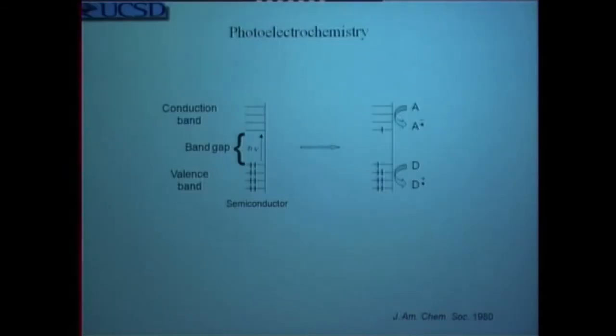Similarly, if there is a hole in what was the highest filled orbital, that hole can be filled by accepting an electron from the donor. So by using absorption on a titanium dioxide particle or an electrode, you can get to the same place that you could by water splitting in that simple experiment you remember from your elementary school days. This is what we refer to as photoelectrochemistry, and it's a reaction which has been elaborated significantly for over 30 years. First publication in our group was in 1980.